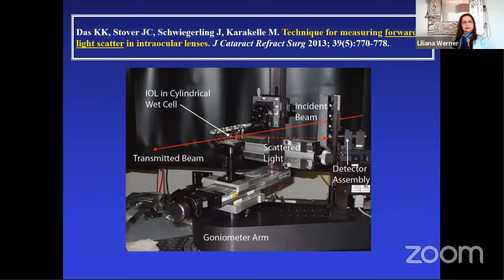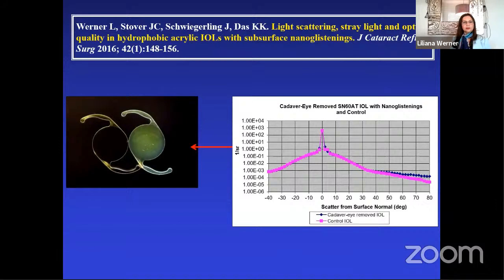There are laboratory techniques that can measure the forward light scattering, which is the light scattered towards the retina with a potential to have an impact on the visual function of the patient. We performed different tests with hydrophobic acrylic lenses showing subsurface nanoglistenings and demonstrated an increase in light that is scattered forward to the retina. However, the values obtained are not expected to cause any negative impact on the visual function. Therefore, IOLs are generally not explanted because of subsurface nanoglistenings.